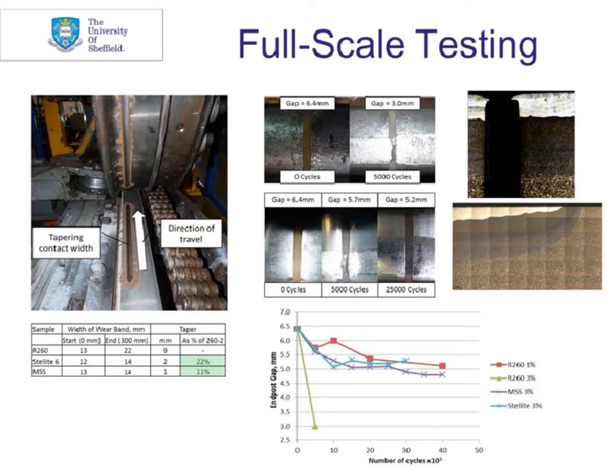If a track circuit shunts, it can be very, very costly. The repairs are very simple to do. You go out with a little Dremel and you cut the material away and it's okay. But by losing that bit of line for a time, a lot of delay minutes accrue. So we looked at the idea of putting a laser clad material either side of the joint to reduce the amount of flow that occurs.